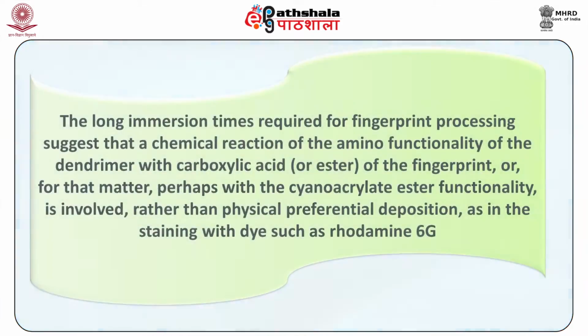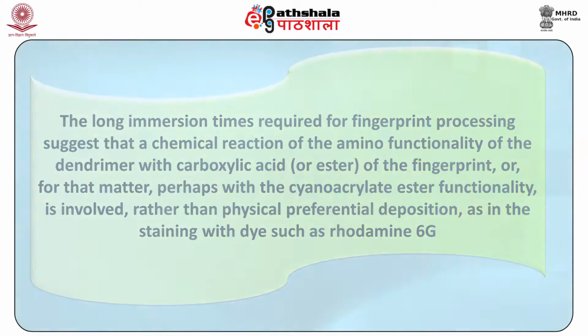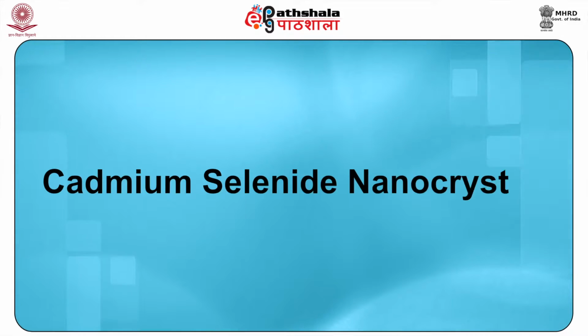Cyanoacrylate ester pre-fumed fingerprints, on the other hand, developed readily on both the aluminium foil and the polyethylene. The long immersion times required for the fingerprint processing suggest that a chemical reaction of the amino acid functionality of the dendrimer with that of the carboxylic acid or ester of the fingerprint, or for that matter perhaps with the cyanoacrylate ester functionality, is involved rather than the physical preferential deposition as in the staining with dyes such as rhodamine 6G. Now we will be studying the use of the cadmium selenide nanocrystals.